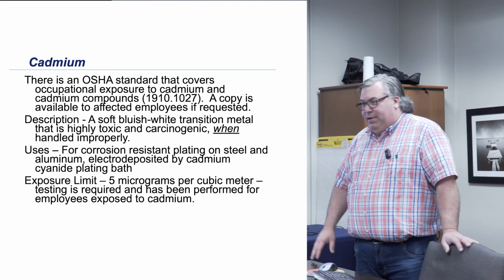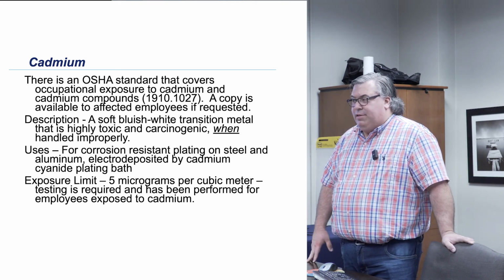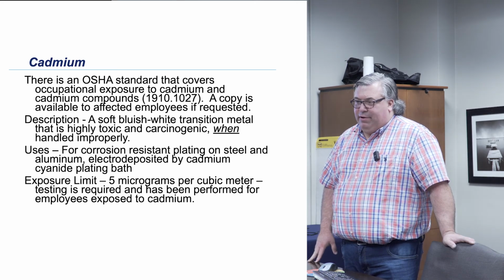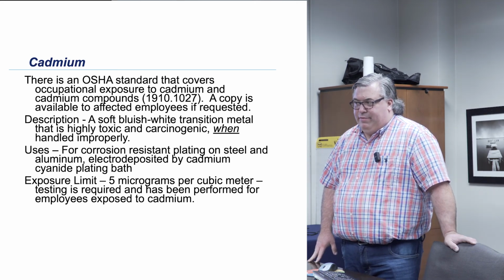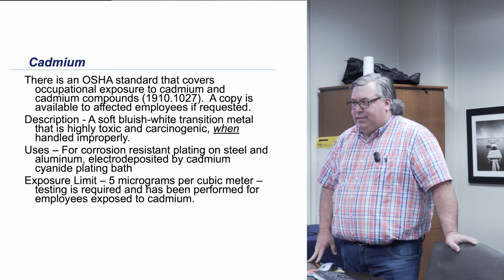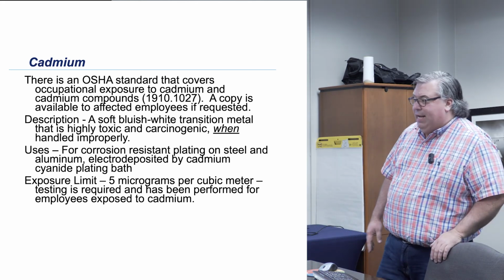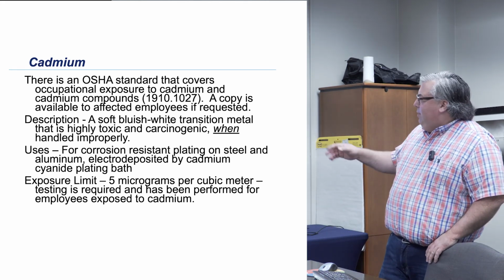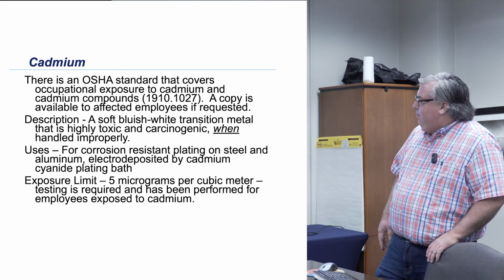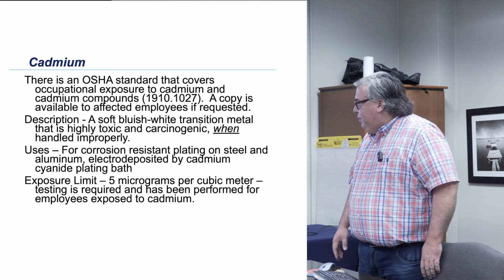Here at Cooperative Plating, we have two cadmium tanks, and unfortunately the government still loves it. The military in particular still loves it because they have drawings from back in the 60s that still call it out, and they're still making those parts. There's been a big push to move away from it, but not yet. Exposure limit is 5 micrograms per cubic meter. Testing is required and has been performed on employees exposed to cadmium.